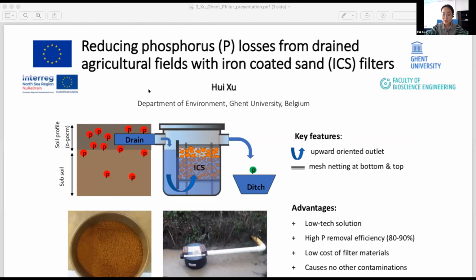So there are a few advantages of our filter. Low-tech solution, it is suitable for individual drains and very easy to install and operate. High performance. P removal efficiency is very high, up to 80 to 90% over several drainage seasons at different locations. It's cheap and safe. As Stefan already presented, the filter material is iron-coated sand, a byproduct of the drinking water industry, so it's rather cheap and doesn't cause any other contamination. Also, this filter has no impact on accessibility and landscape. Therefore, this filter could be a potential solution to reduce P loads.